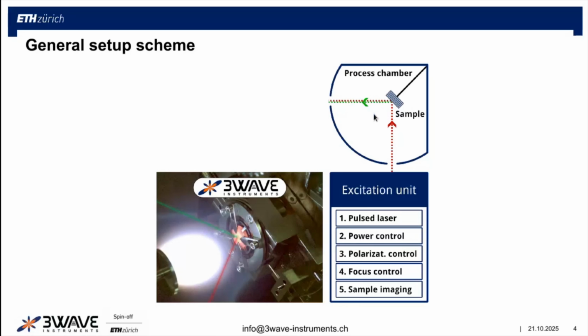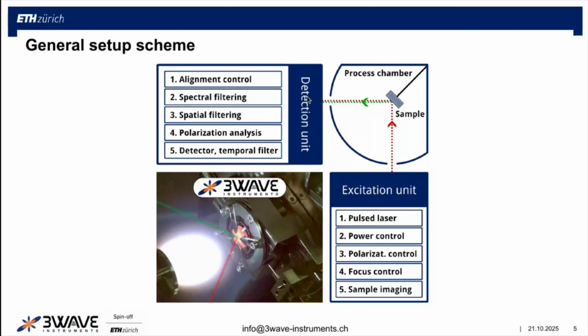And then here we have our process chamber with the sample. The sample, as Manfred introduced, generates second harmonic light, which is detected by the detection unit, the second box attached to the chamber. And here we have many features, for example, an alignment control that makes sure that we have a good pointing onto the detection unit, and also that the light travels through the optical system as it should. Then we have multiple filtering methods. So we have spectral filtering, we have spatial filtering, and finally also some temporal filtering on the detector. And similar to the excitation unit, we also have polarization analysis and polarization control for the second harmonic light.